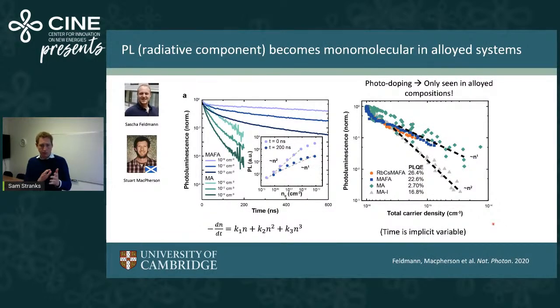So this is all on methyl ammonium lead iodide. I just want to give an example when we start alloying these systems and we start putting in other components other than just methyl ammonium lead iodide. And so this is an example where we start putting in formamidinium, which is a slightly larger organic cation still. We see already a very big change in the kinetic of these materials.